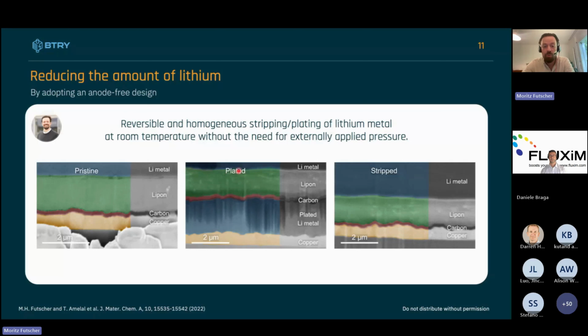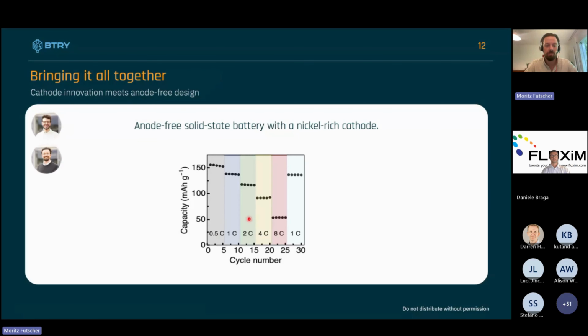And then this would be basically in a charged state of the battery. And then if we discharge or remove the lithium, we can fully remove it again. And this really allowed us to make an anode-free battery or a lithium reservoir-free battery, where we don't have any anode during the fabrication, but then the anode is only formed once you charge the battery the first time.